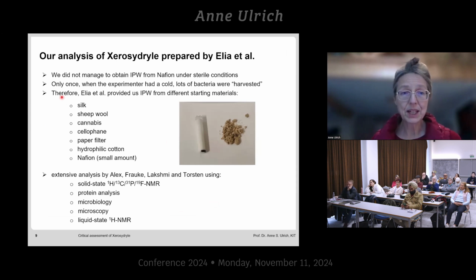Several samples prepared from silk, sheep wool, etc., and also from Nafion, technical membranes, although the latter sample was only a very small amount because they say that is the most difficult material from which to prepare Xerosydryle. And here you see a photograph of some brownish material. It was actually a bit crunchy and hard. Here you see a special NMR tube.